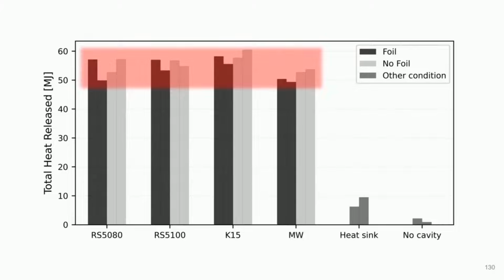You can also see that whilst the presence of the foil facer might slightly change the time it takes for escalation to occur, it does not drastically influence the total amount of energy that is eventually released for any of the insulation products. This is yet another indication of the dominance of the Reynobond PE ACM to this fire.